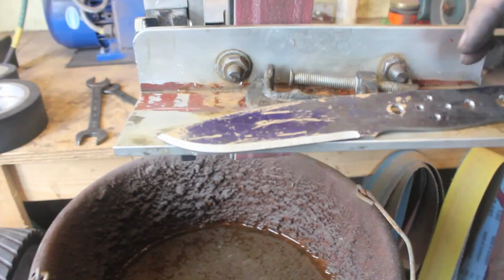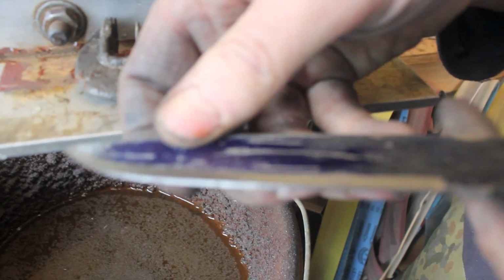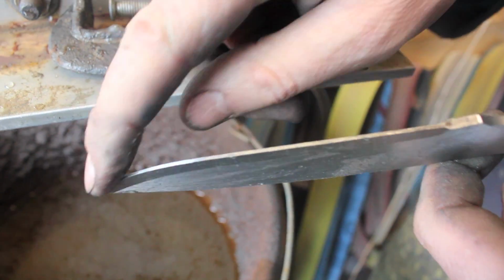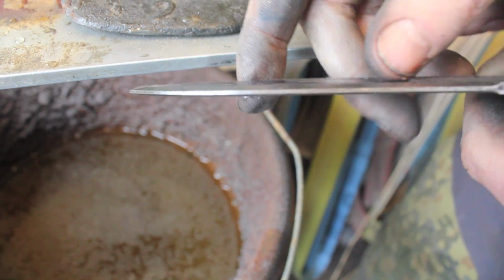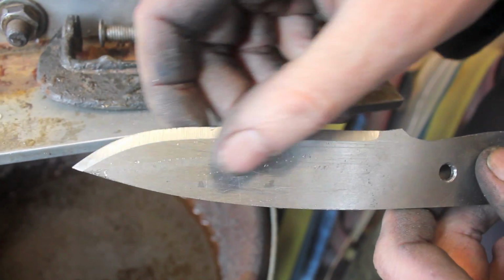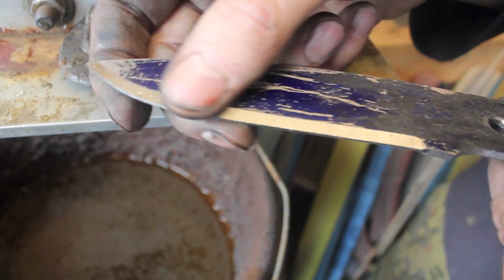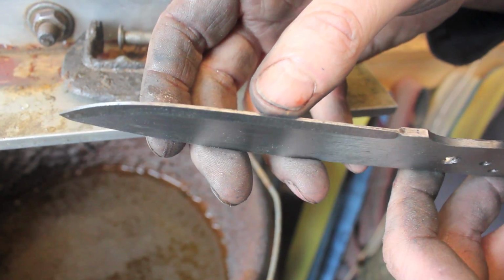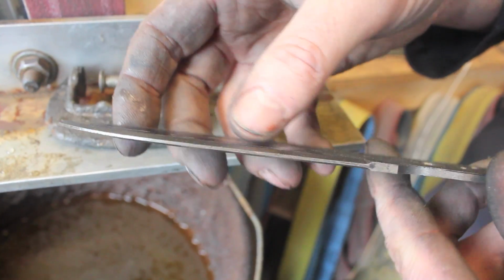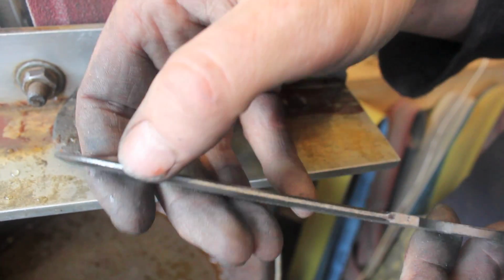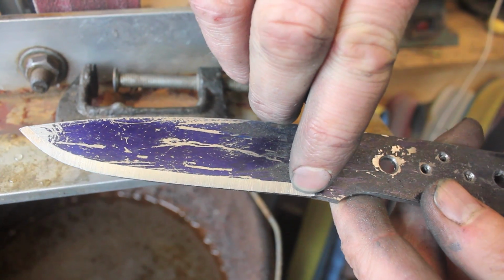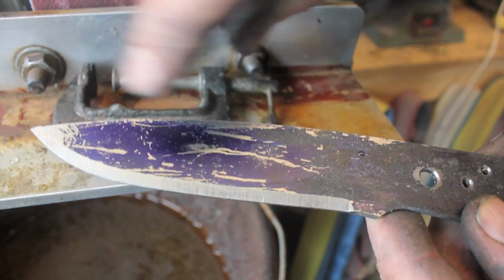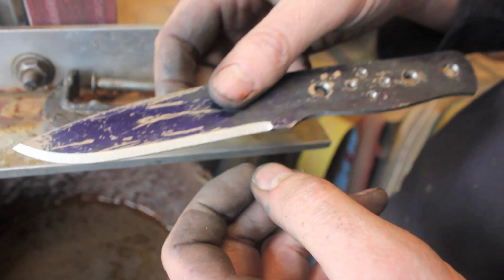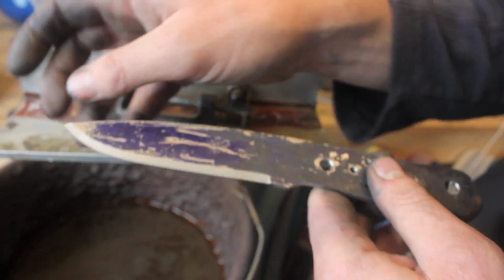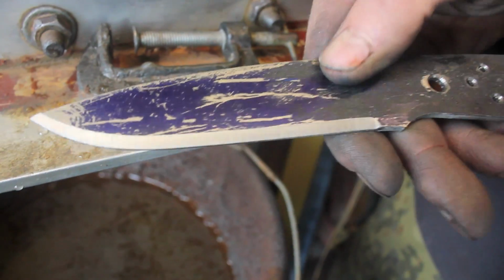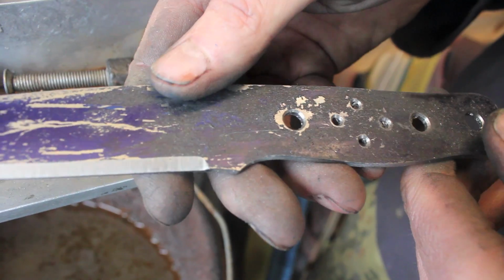Okay, so there you go. So you've taken the Yeah, I've taken the edge down. That's about 1.5 mil in thickness there. What happens during the heat treat process, we do lose a little bit of carbon from the surface of the steel, and so this enables me then, after heat treat, to grind down to the cutting edge, and I'll grind to where I get a good strong burr, and the cutting edge will be up here, about 1 mil up here, 1.5 mil higher than it is now, and that means that all the decarbed steel is eradicated, and we're into good clean steel then, which should be hardened and tempered at the correct Rockwell value.